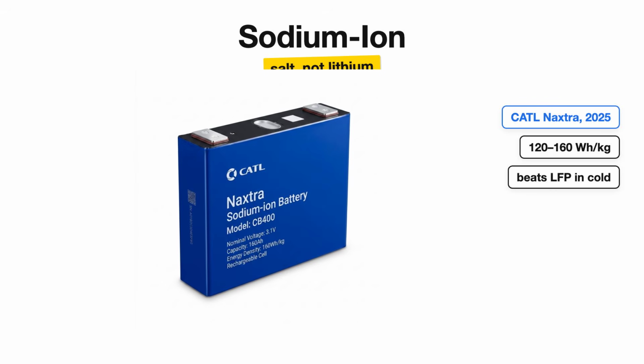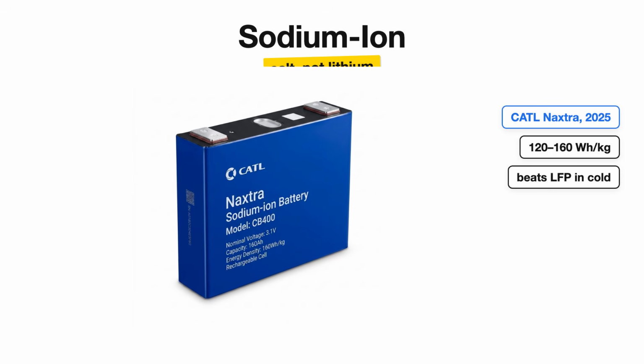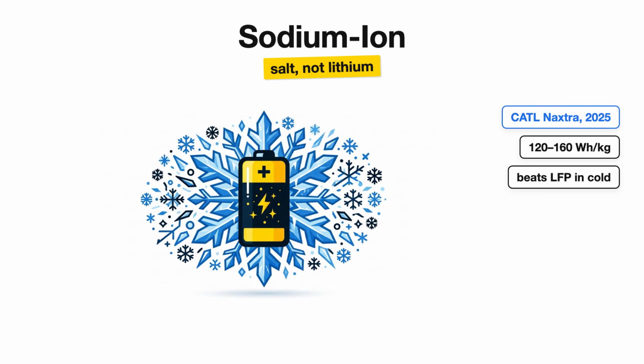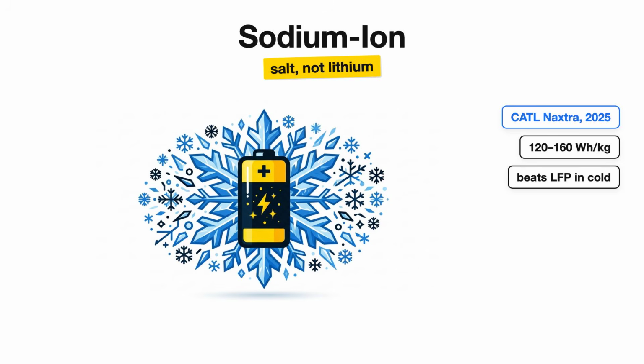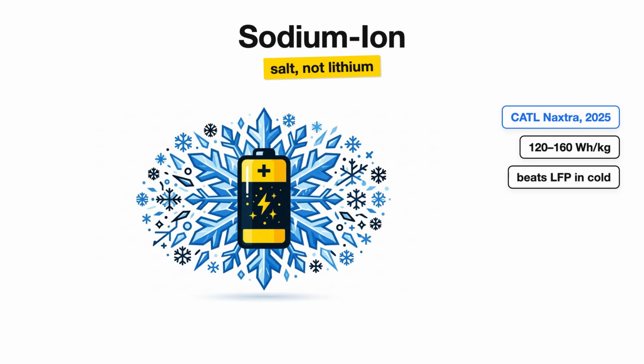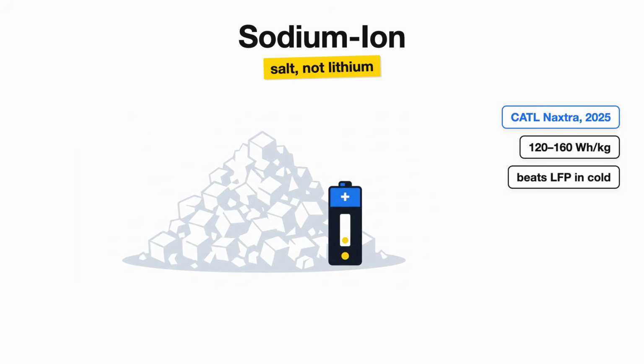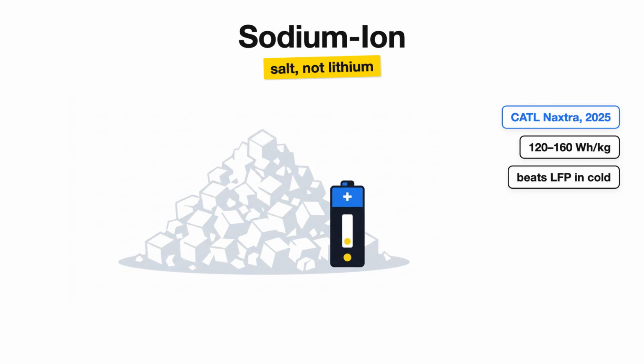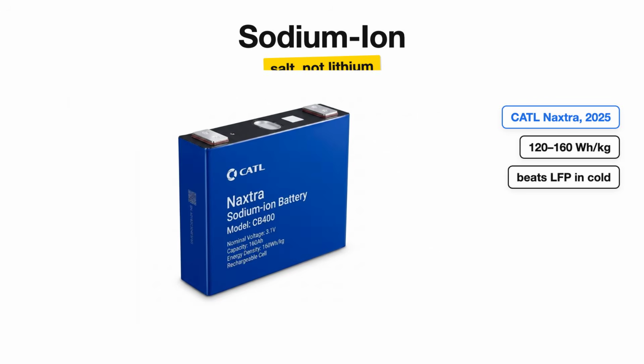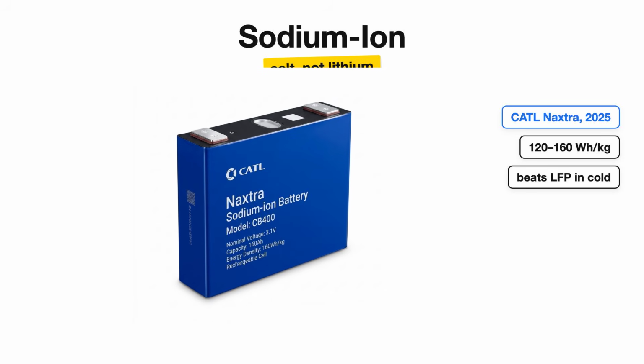CATL entered mass production of their sodium-ion battery, called the Naxtra, in 2025. Energy density sits between 120 and 160 watt-hours per kilogram, approaching LFP territory. It also outperforms LFP in extreme cold. At -4 degrees Fahrenheit, sodium-ion cells hold their capacity better than lithium iron phosphate. If CATL scales this successfully, it breaks the geopolitical dependency on lithium mining almost entirely.